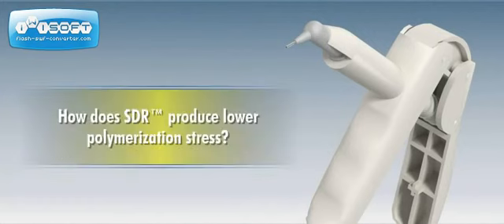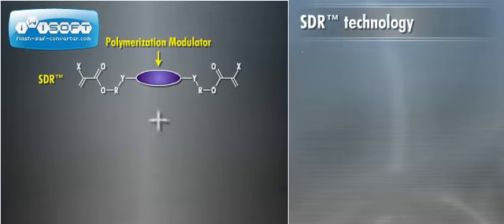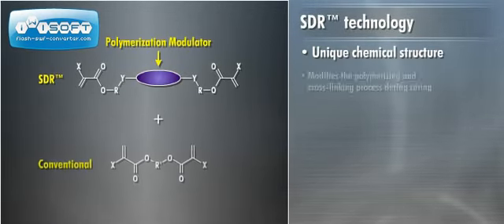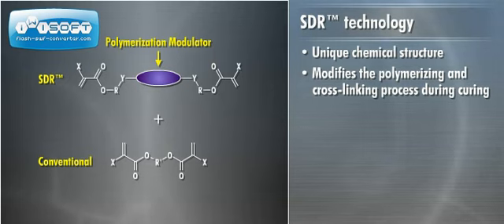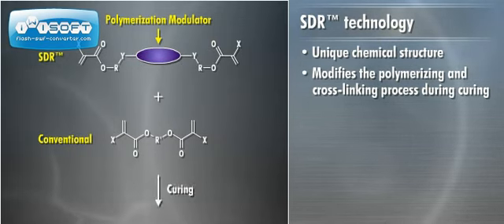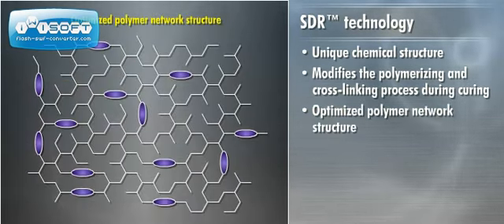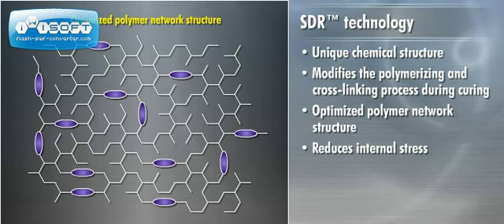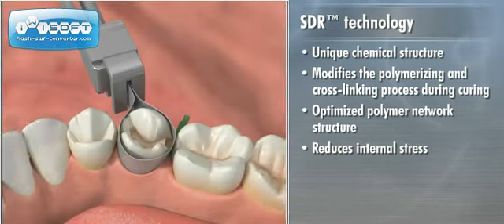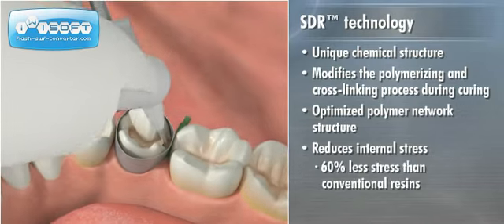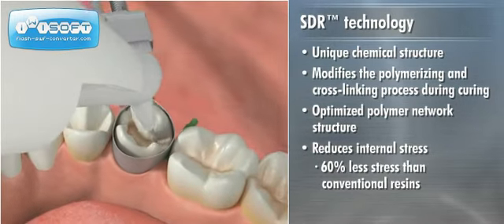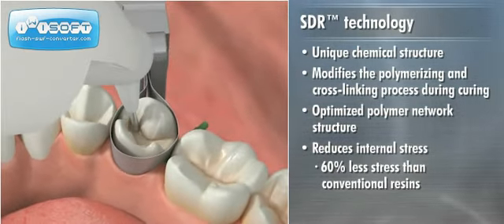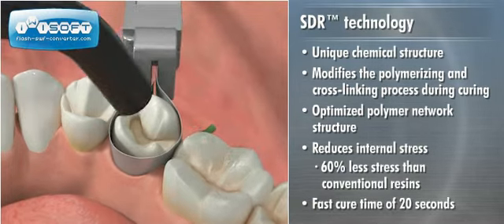How does SDR produce lower polymerization stress? SDR technology has a unique chemical structure which modifies the polymerizing and cross-linking process during curing to form an optimized polymer network structure with reduced internal stress. In fact, this translates to 60% less stress than conventional resins and without sacrificing a fast cure time of 20 seconds.